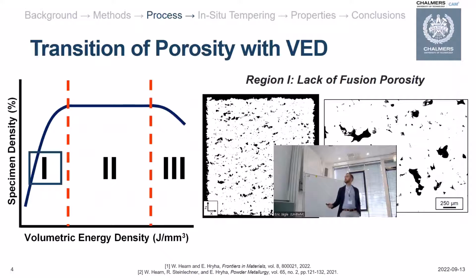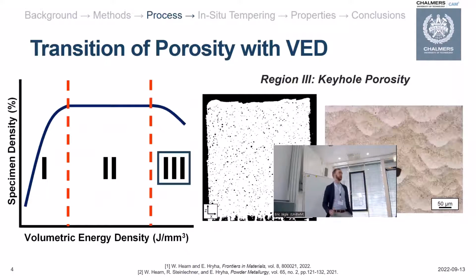These are some very nice partially sintered or unmelted particles inside them. In the same way, when you go too high in your energy input, you also have a pretty poor specimen density, but in this case, instead of large irregular pores, you're having more rounded pores that, when you do some nice etching, you see the melt pool boundaries and clearly are related to keyhole-based porosity.